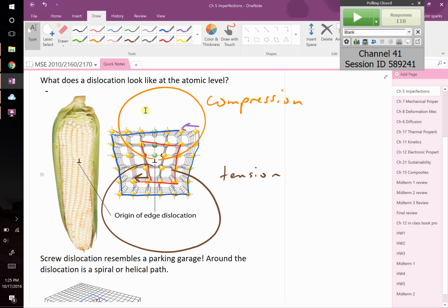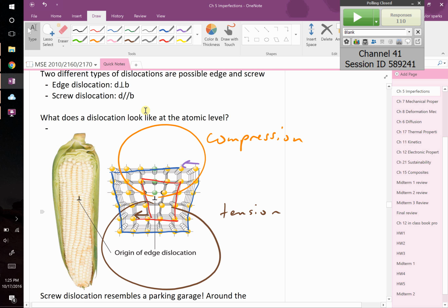So think about this. Let's say you've got a defect, right? The niobium going into the titanium, for example. Niobium's smaller than titanium. Is it? Let's say it's smaller. I don't know if it is. If it's smaller, where's it going to go in the lattice? It's going to go somewhere where it minimizes lattice distortion. If it's smaller, then where's it going to want to sit? If there's a dislocation nearby, it's going to want to sit right here, right? So it becomes really important when you have impurities, because impurities and dislocations have like a symbiotic relationship.